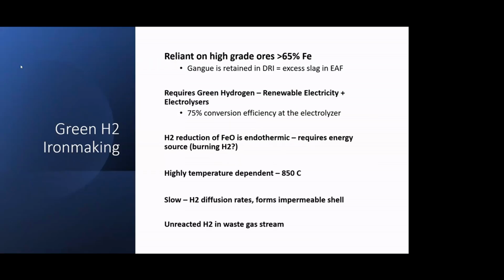So the issue with hydrogen steelmaking is it is reliant on high-grade ores, which have to be above 65% Fe oxides. The reason for that is that the impurities are retained in the direct reduced iron. There's no opportunity in that process to get rid of those. And so as a pellet feed to an arc furnace, if it's high in gangue, then you have a lot of slag and a low tap weight, and production-wise it doesn't work very well.